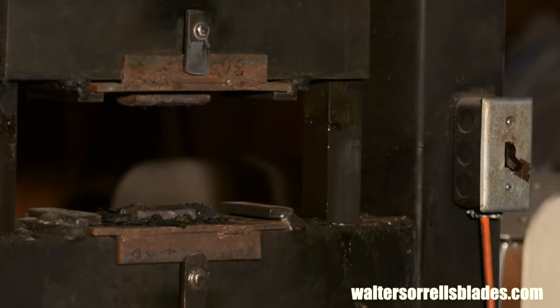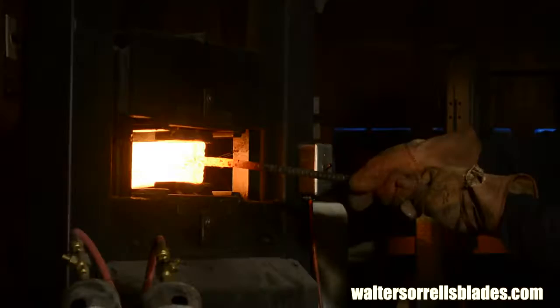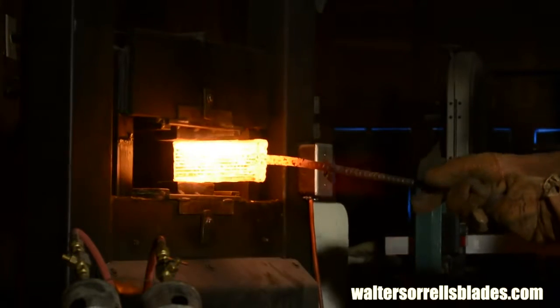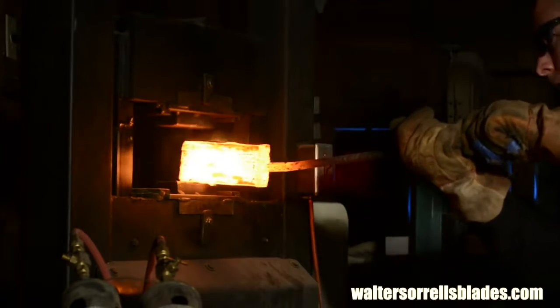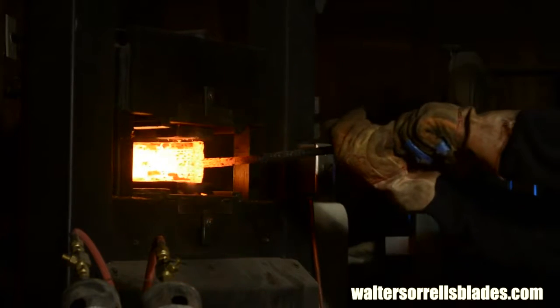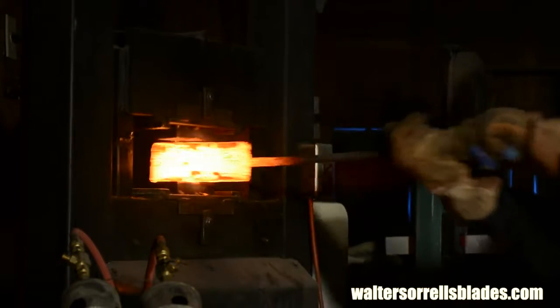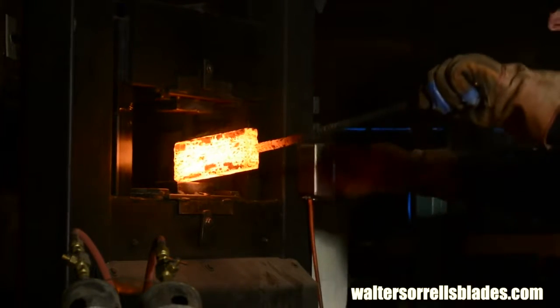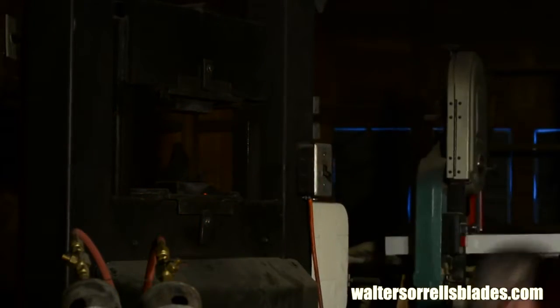No matter what though, you want to set that weld super quickly while the entire billet is at welding heat. The welds are still weak, so if you get too aggressive, you can cause them to shear. First time out, we're just sticking that weld together, not moving it.